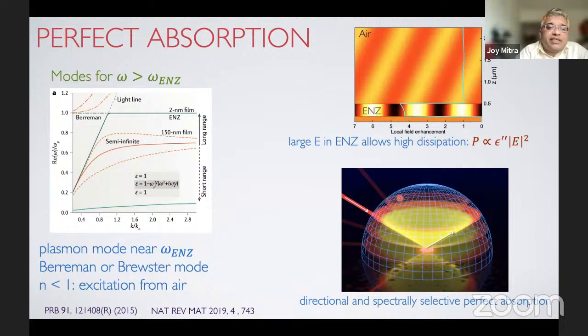Now, the real value of this understanding comes from the fact that plasmons cannot be excited in metals directly from air simply because of the wave vector mismatch. But now, due to this Brewster or Berreman mode existing on the left of the light line, and the fact that the refractive index of the material is actually less than 1, it is possible to excite these modes from air. Okay, so we can excite these Berreman modes from air directly onto this material.